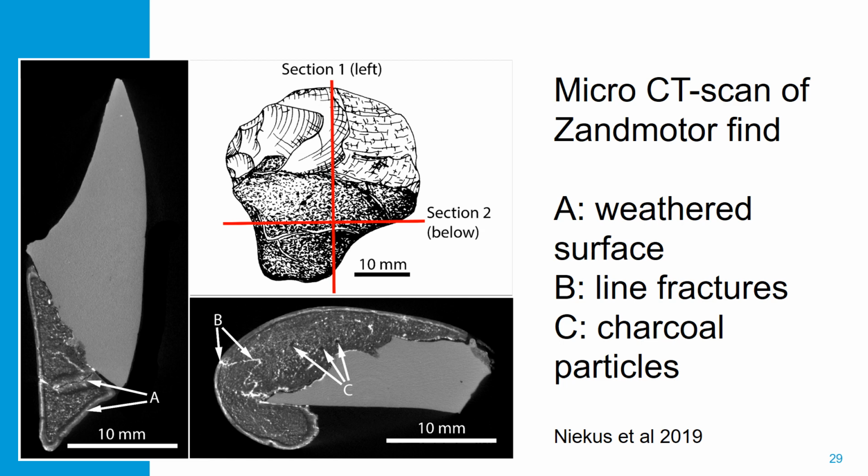From our experiments, we know that this only happens when the tar is completely liquid and when it drips into the container or the catchment. With the other methods, we only see this with the oven method, and we don't see this with the other experimental methods. We don't find this pattern of contamination.